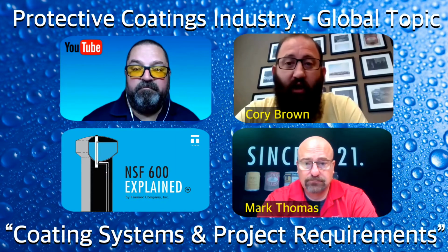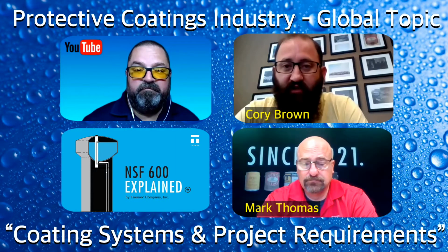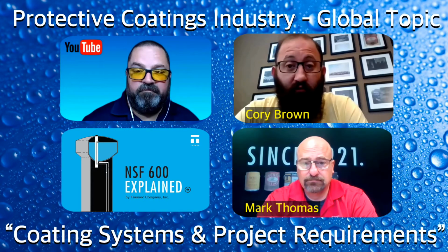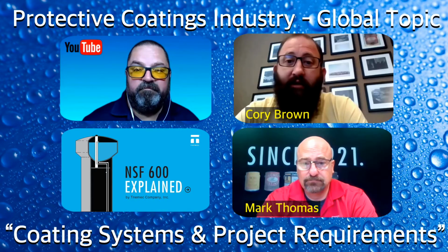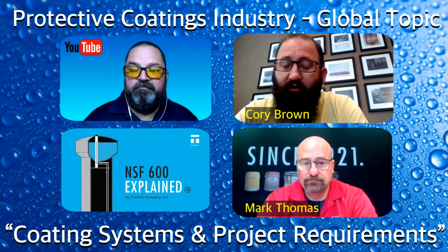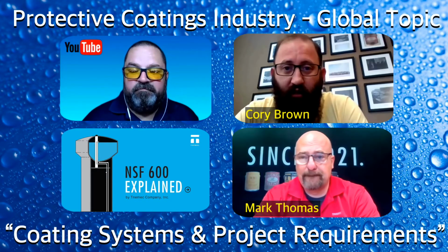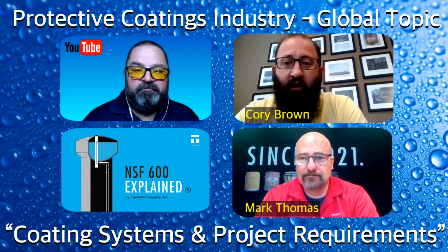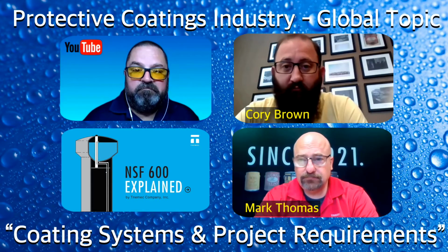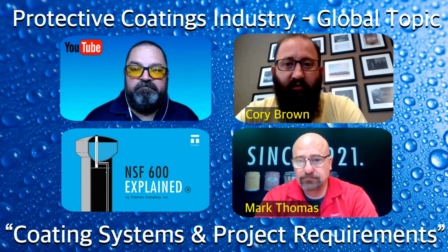That's almost twice what we've issued in the past. There's some SSPC standards out there that only call for a mil of anchor profile. A lot of our old epoxy linings called for 1.5 mil anchor profile, but we're going to increase that now up to 3 mil profile.